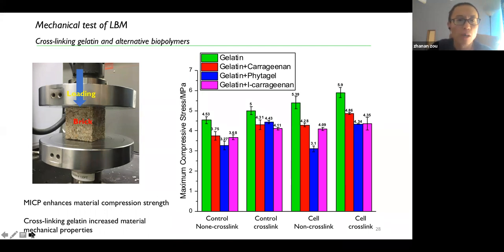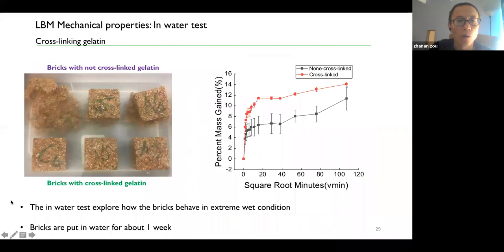And apart from this mechanical test, if we move to the next page, we also carried out some other tests, which is an in-water test. The aim of this test is to explore how these bricks behave in extreme conditions. So in this experiment, we simply put all the bricks in the water. We immersed them in the water for about 1 week. As you can see in the left picture, the top 3 bricks are made with gelatin that is not cross-linked, while the bottom 3 are made with gelatin that is cross-linked.